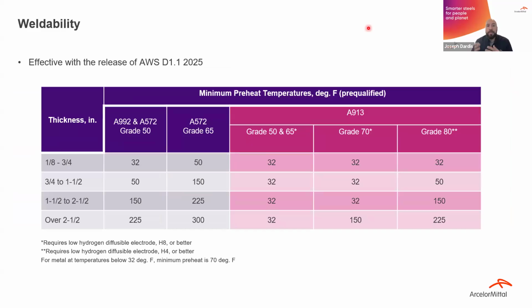So if you look at this chart, the preheats for A913 are generally a lot lighter than your conventional A992 or A572 grades. For grades 50, 65, and 70, you often don't need to preheat at all, and for grade 80, the preheats actually match A992 and A572 grade 50. So you're getting all that additional strength, but you're improving your weldability and not having to preheat that steel nearly as much, or just the same as A992. So there's a huge weight savings there by using an increased yield strength, but you're also saving on the fabrication end as well in a lot of cases.